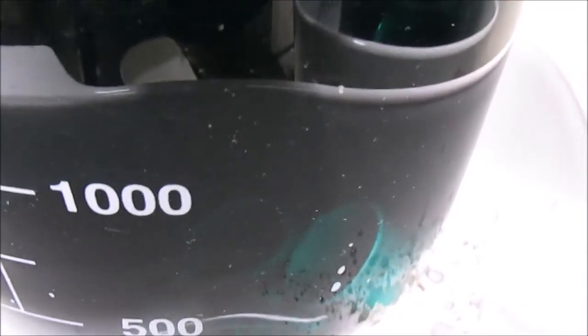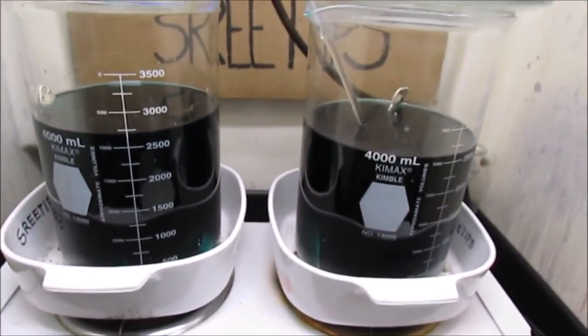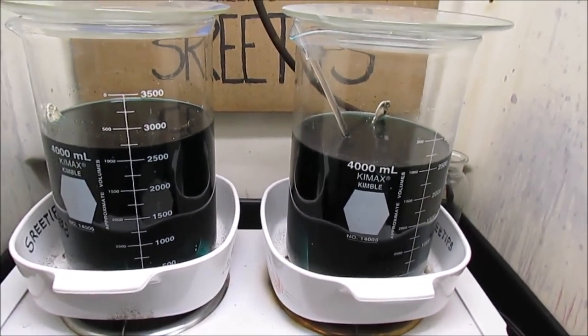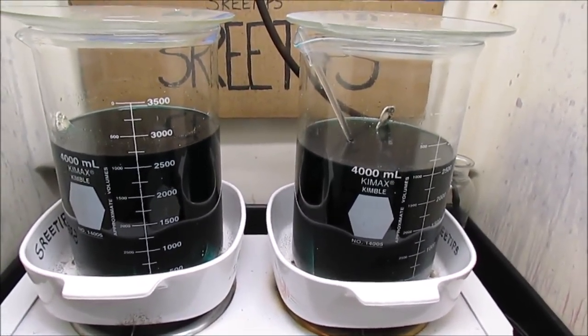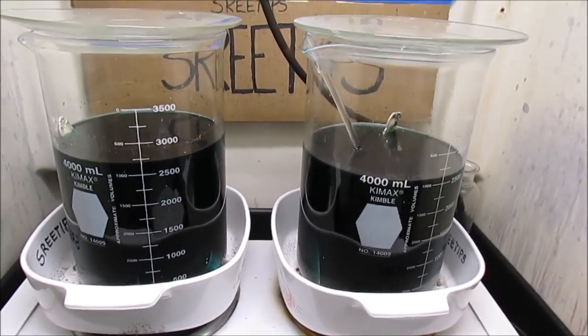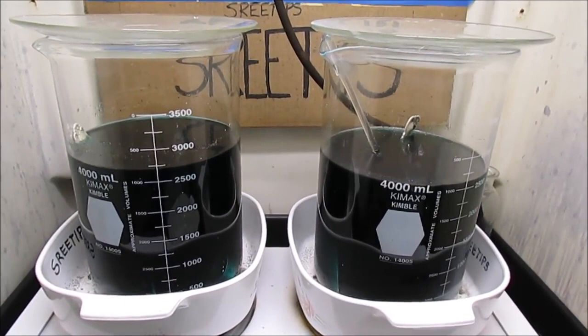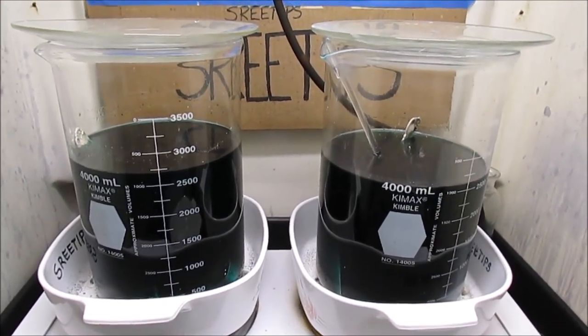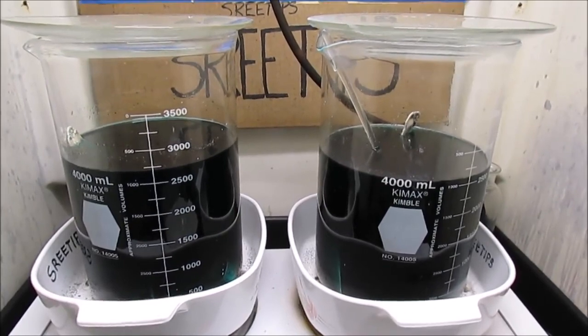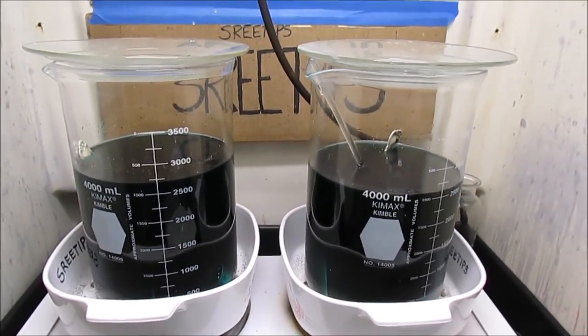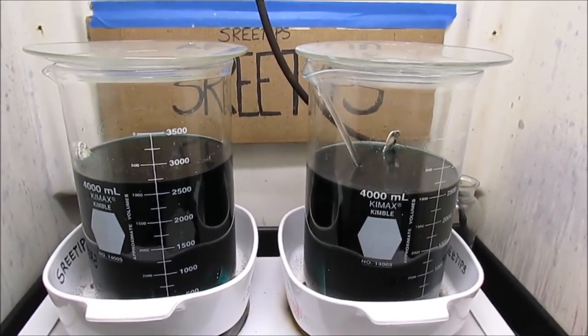This is important to have because we want some leftover silver in the bottom of the beaker to ensure that we've used up all the free nitric acid. When I go to the next operation, which is cementing this silver out with copper, I do not want a bunch of free nitric acid in there because it will needlessly consume the copper and it will dissolve the silver just as fast as it cements out onto the copper. So I want to consume all the free nitric acid out of these containers before I do this filtration. And I'll go to the next step.